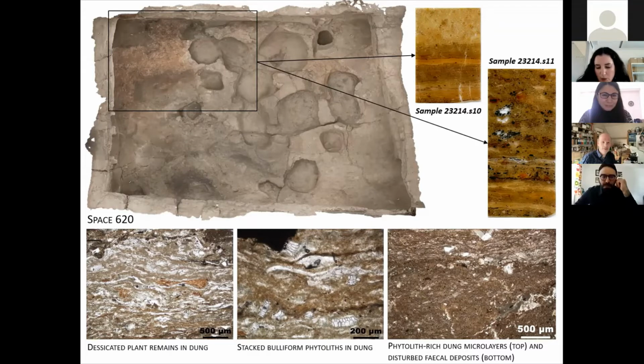These are typical components of midden deposits that are here found embedded in these dung laminations, possibly as a result of redeposition and trampling, or more likely due to the fact that discard activities were not discontinued in this area during its use as a pen. It is possible then that the alternation that we see in the samples between pen and midden deposits is related to seasonality and life cycles.